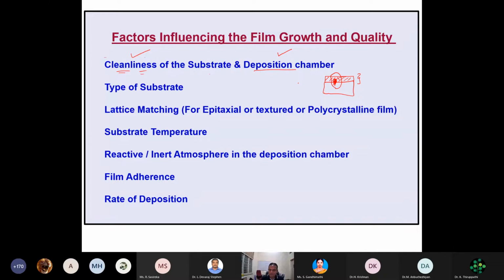Because every second you will see that a lot of dust particles and carbon from the atmosphere keep on depositing on your substrate. So every time you have to clean the substrate ultrasonically, immediately load it into the chamber and start your deposition to minimize the surface contamination. Likewise, your deposition chamber also should be very, very clean.